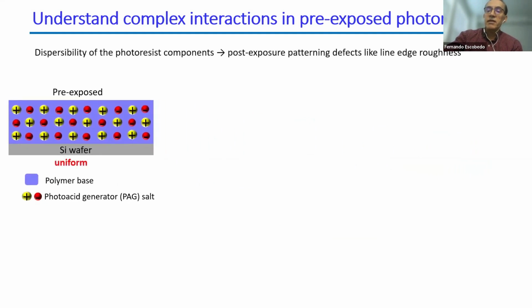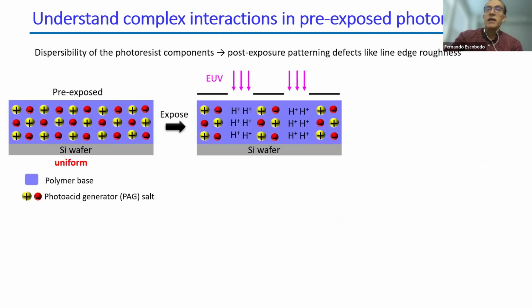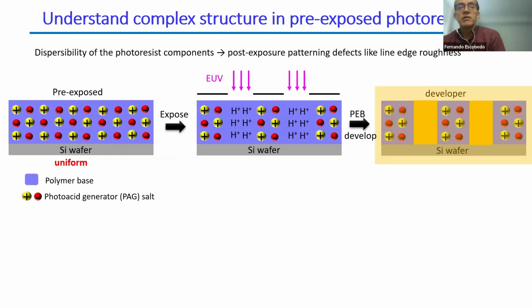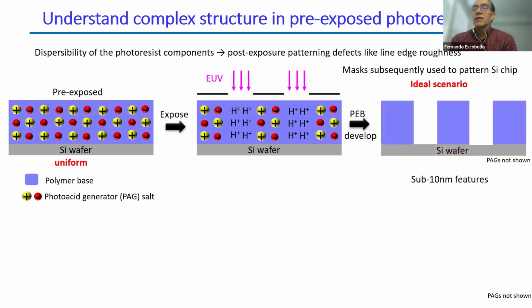So the idea is that if you take this film of photoresist and expose it using this very precise tool, the EUV, it's going to decompose or activate these PAGs, this photoacid generator. So it creates a number of free radicals, and then eventually it creates acid. The acid is going to react with some of the polymer, basically decomposing it, so that once you apply a developer, which is an aqueous-based solvent, this solvent is going to dissolve the parts that were exposed and leave more or less untouched the parts that were not exposed. You can create these very nice features. And of course, it's in those features that you will continue the processing to create these microchips.